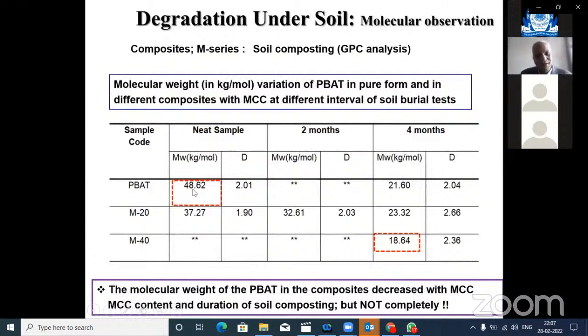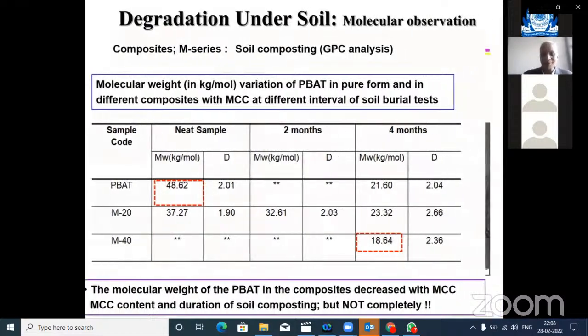You just put your eyes here. I just want to guide you in these two samples. This is with a polymer with 40% microcrystalline cellulose. When we look at the molecular weight of this material with the same polymer with 50K molecular weight, we see after 4 months there is a drastic decrease in the molecular weight, average molecular weight from 50 to about 20. But still, this is not monomer. This is still a polymer, 18,000 grams per mole. So these things, even if they appear to disappear inside the soil, they make microplastics. This is the indication.